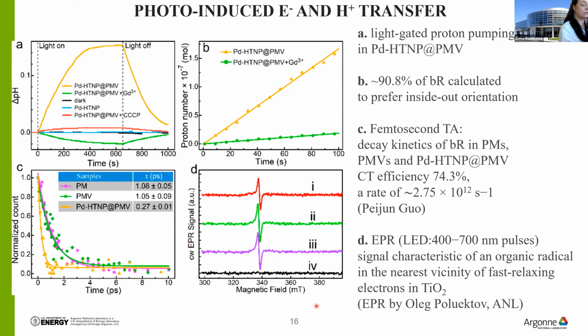And then we moved also to characterization using EPR. It was done by Oleg Poluektov, I'm saying up front, because it's a sophisticated technique. It was demonstrated that upon light illumination, there is formation of an organic radical, typical for a radical in near proximity of excited titanium dioxide. And also it's important that at low temperatures, at 10 kelvins, when the light was off, the charge separation state was preserved.